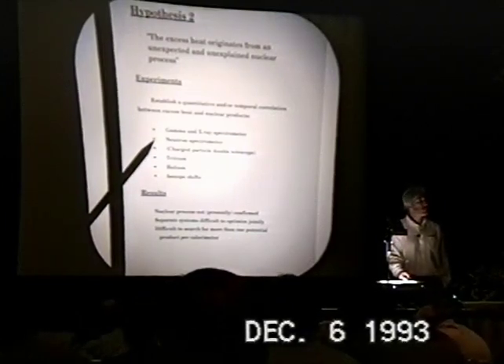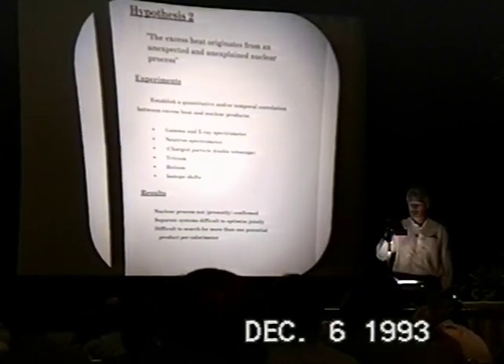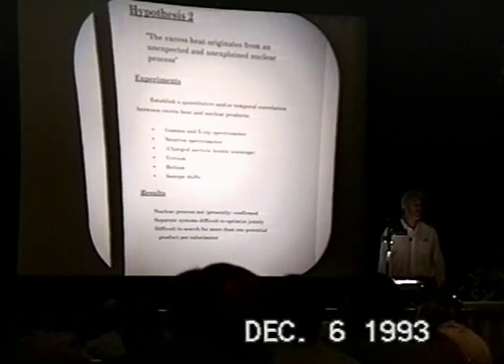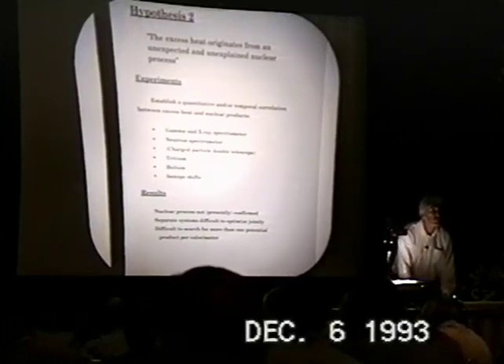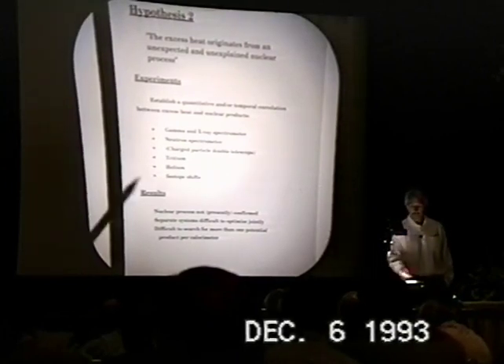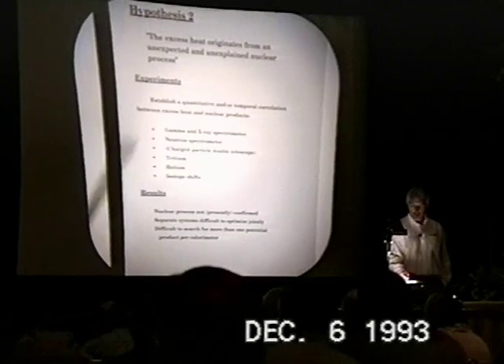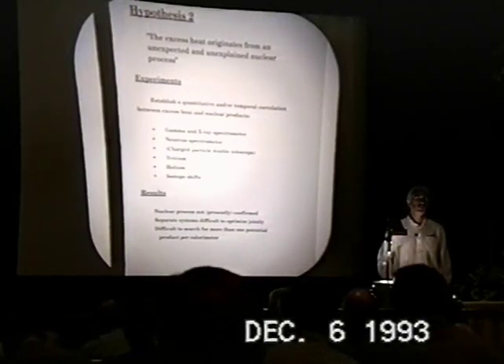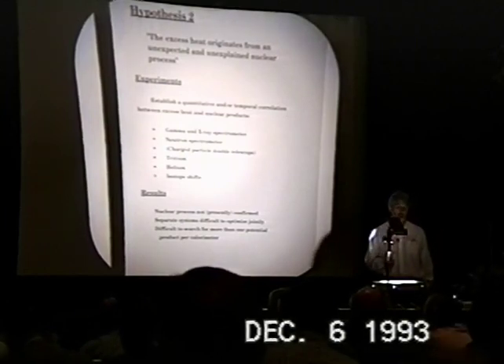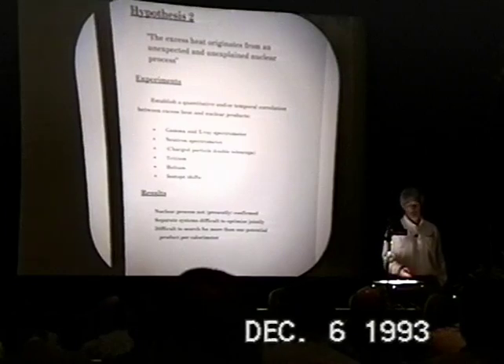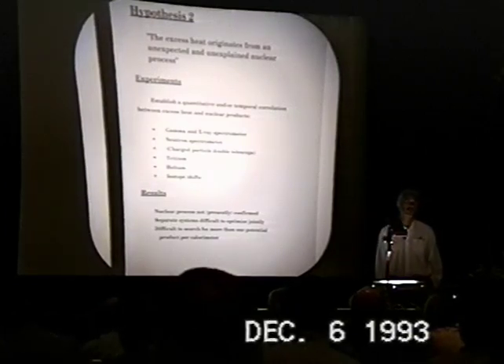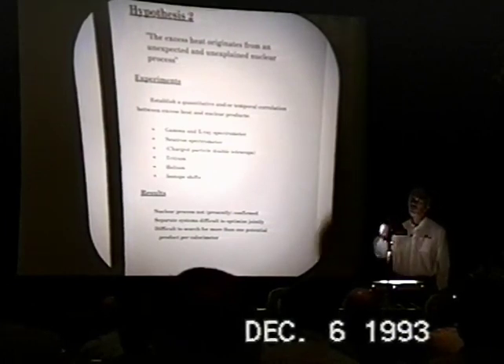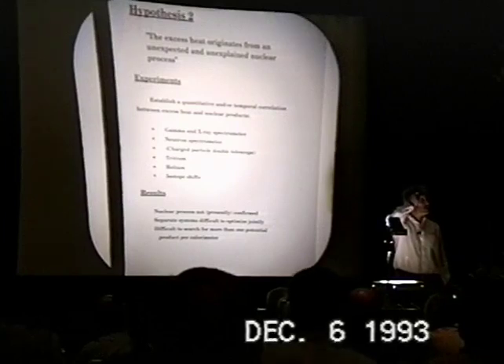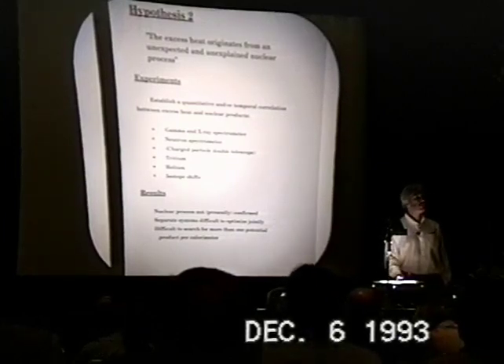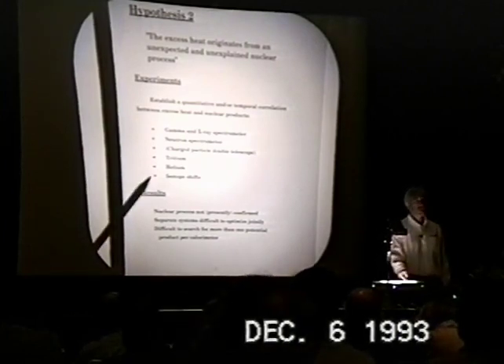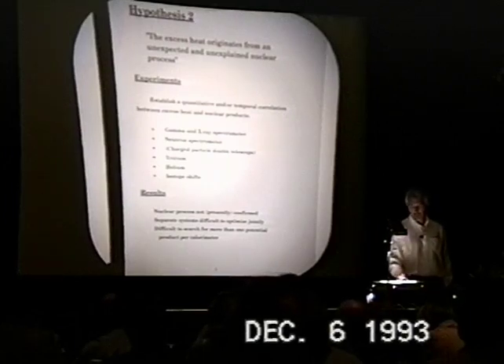We're presently establishing a neutron spectrometer to go after the traditional products of nuclear processes, to determine not only to what extent they are present, but to what extent they're not present, with some sort of upper bound on the production of these species. We also have in mind at least a charged particle telescope, not conveniently used in electrochemical experiments, which most of our experiments presently are. We investigate tritium as a potential product, helium as a potential product, and isotope shifts of deliberate additives to the lattice, such as lithium and boron. The lattice constituents itself, palladium, these necessarily, at least in our hands, are post-test analyses.